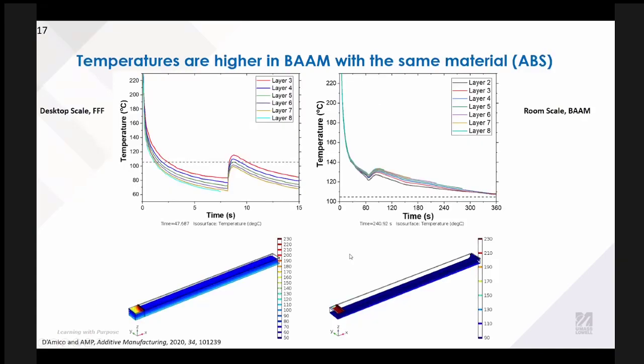We were interested in extending our model from the FFF scale to the BAAM scale, and then doing comparisons across these, trying to understand what's important for material extrusion at these different length scales. One of the things that we see is that the temperatures are just a ton higher. And so here we're simulating the printing of ABS, and we see that our temperatures are much higher for much longer in these prints.